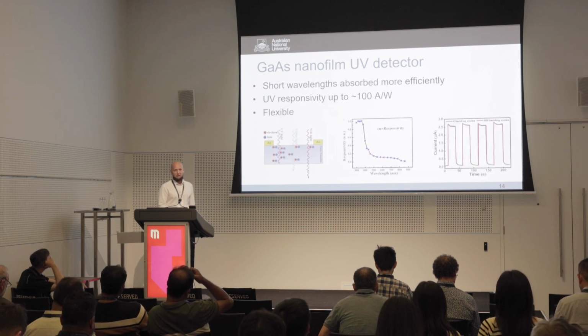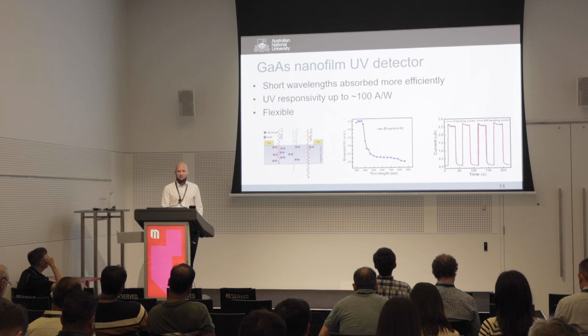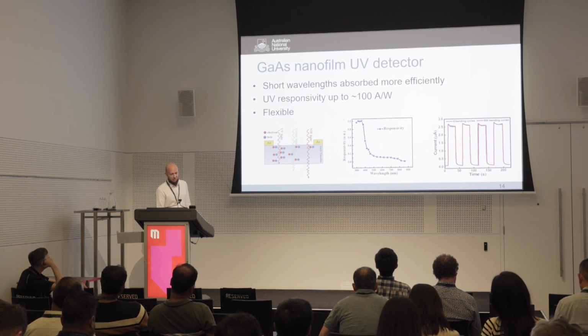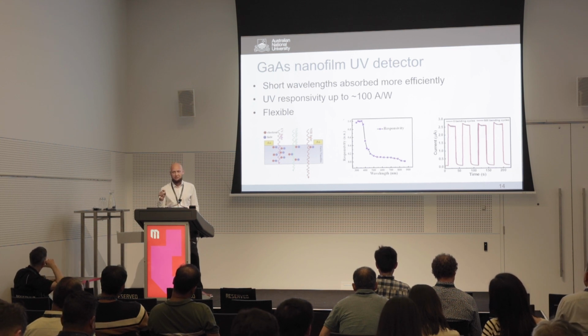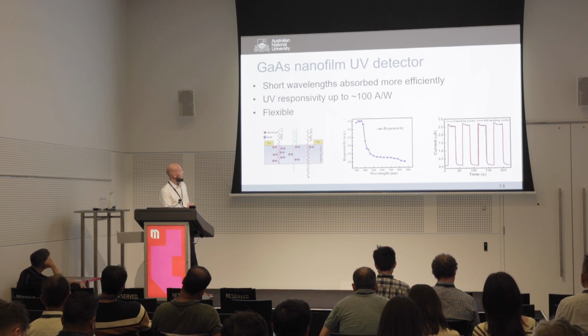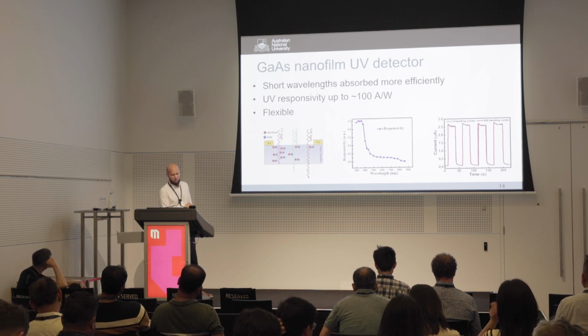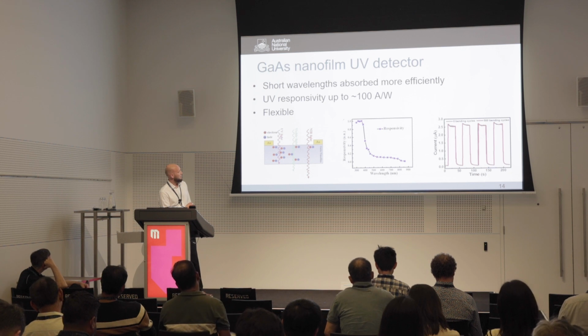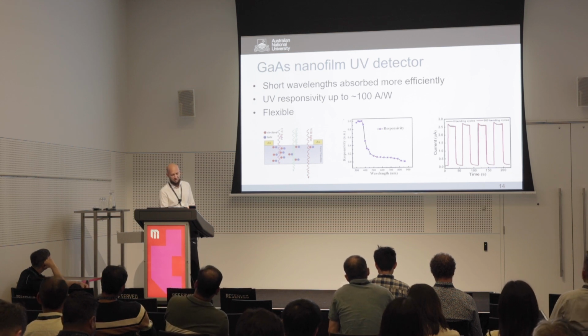So gallium arsenide is typically used as an infrared photodetector. So how come this one is an UV photodetector? So this is because short wavelengths are absorbed much more efficiently within this very thin layer of material, which is shown schematically here. So UV light is absorbed almost completely, and it generates a significant amount of electron hole pairs, whereas visible and infrared light pass mostly through and don't generate much current.